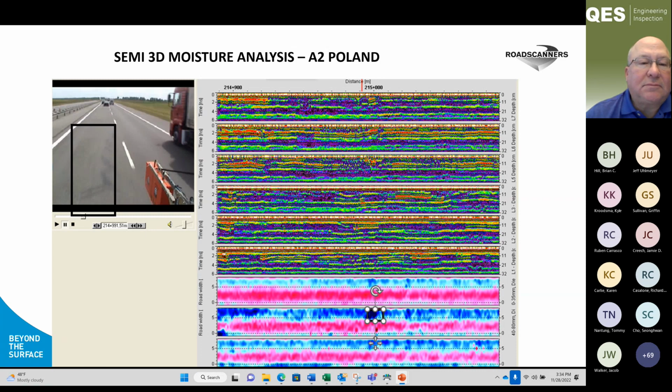And then we made the moisture analysis. And in this case, what you can find also, at that time we found also on the 2 gigahertz data and coreless data, when we are using 2 antennas and using velocity analysis. So we found a clear correlation with the high moisture content in certain layers.